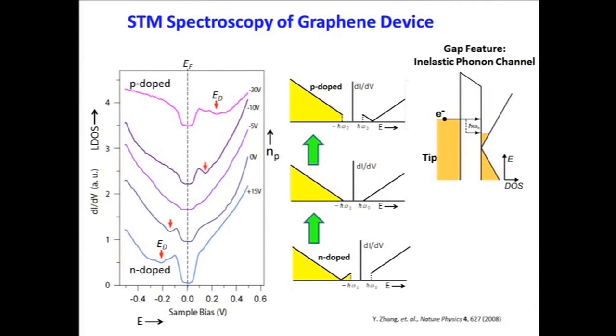Here, this little dip, that feature moves with gate voltage, so that tells us that it's a band structure feature, and in fact, that is actually due to the Dirac point. So you can see the Dirac point moving as you would expect as you p-dope the material.